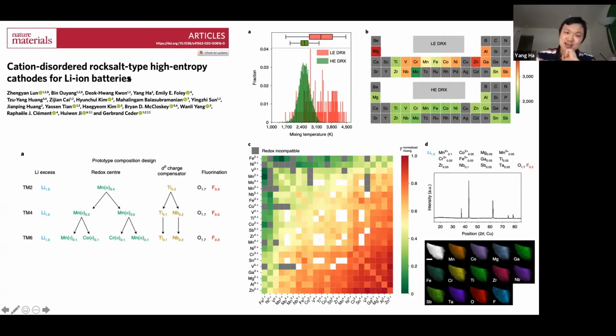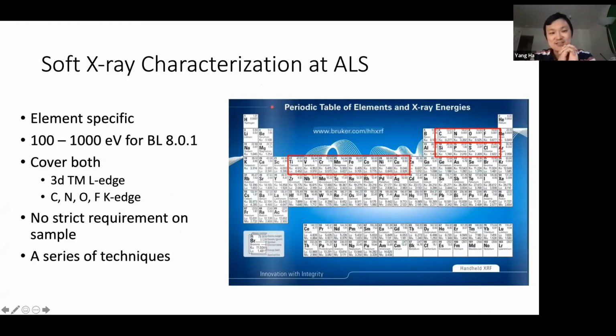So here we use X-ray spectroscopy. The reason X-ray spectroscopy is nice is, number one, or most importantly, it's element specific, which allows us to track the behavior of each individual element independently, one at a time, while you have a mixture of soup. So in the beamline I'm working at, beamline 8.0.1 at the ALS, it's a soft X-ray beamline, covering from about 100 eV to 1000 eV. So this energy range covers all the 3d transition metals and the common anions like carbon, nitrogen, oxygen, and fluorine.